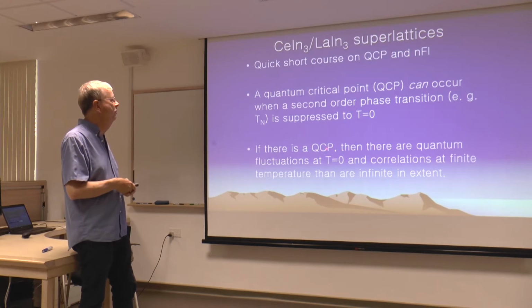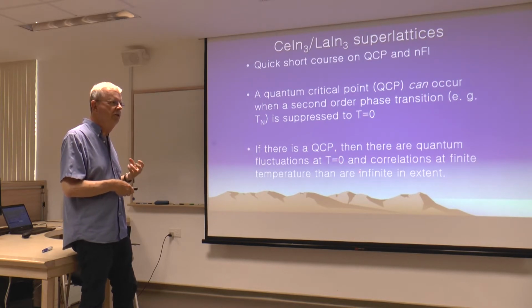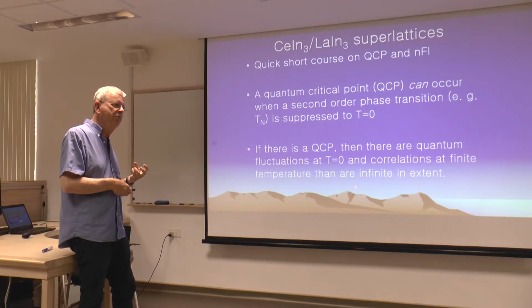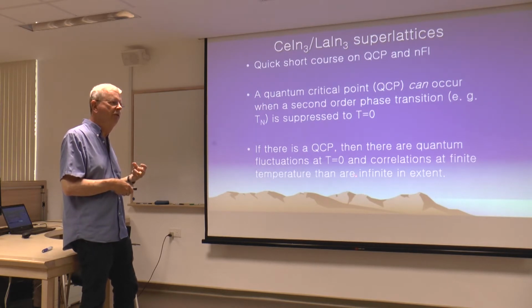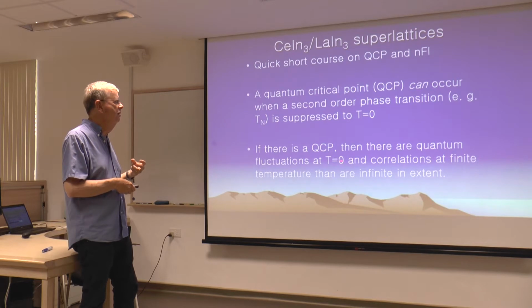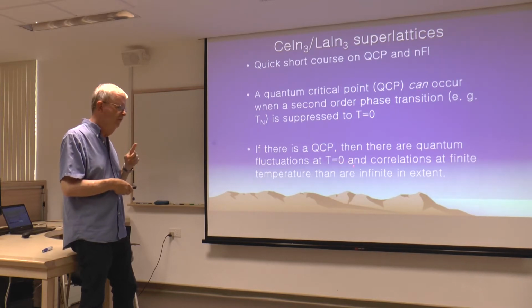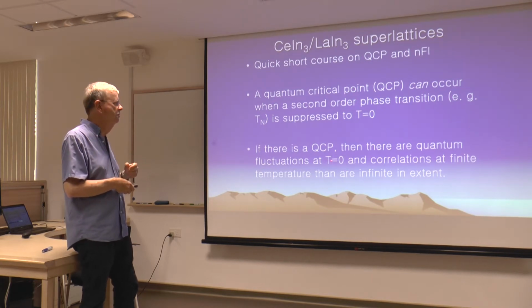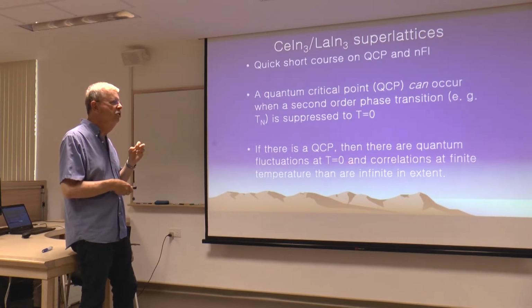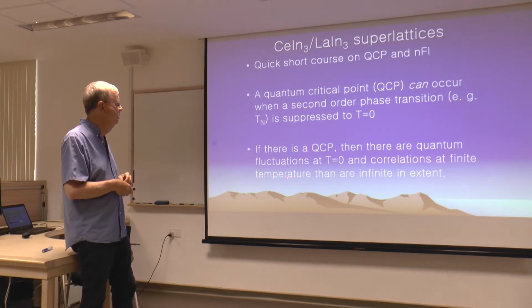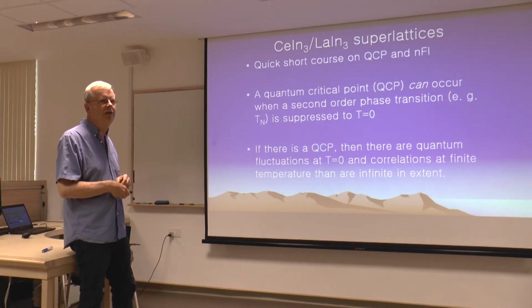So if there is a quantum critical point, then the neat thing is there are quantum fluctuations at T equals 0, unlike a classical transition at finite temperature where you have classical fluctuations above the ordering temperature. If you suppress the second order, not first order, not ferromagnetism, if you suppress the second order phase transition, superconductivity also works, second order phase transition to T equals 0, exactly at that point in the phase diagram, there is a huge effect at finite temperatures because the fluctuations become infinite in extent.